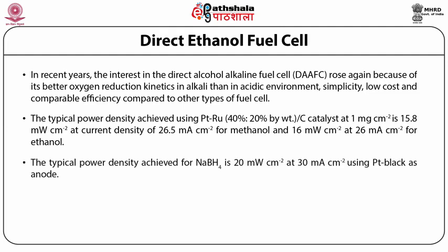The typical power density achieved for NaBH4 is 20 milliwatt per centimeter square at 30 milliampere per centimeter square using Pt black as anode.